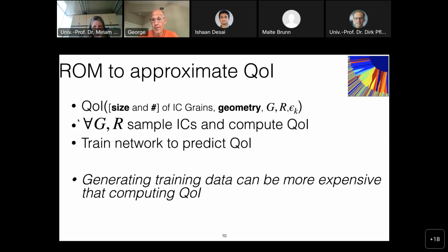Or the power statistics. And then from that, we can sample, if we have the reduced model that basically given as an input these parameters, it returns the quantities of interest, which is, for example, the grain size distribution and the orientation, we can sample. Then if this is very fast, we can sample this input, and then we can produce statistics of our quantity of interest. But the goal is essentially to train the reduced order model.